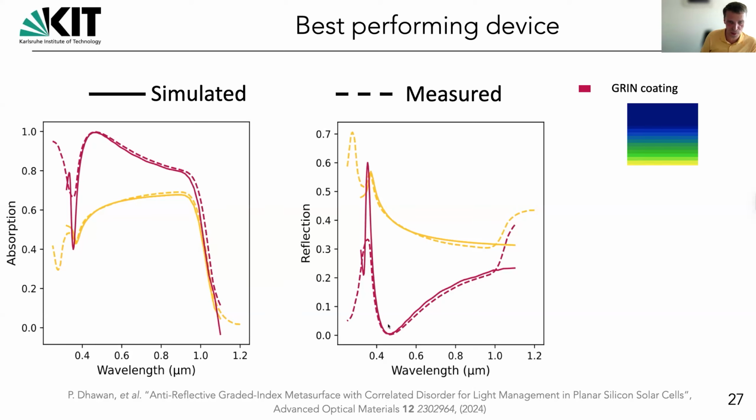So we see that we suppress reflection at design wavelengths, which is very good. But this is not fully broadband possible because we also had only a finite index contrast available, because we have been considering, as I said before, only this titanium dioxide and alumina